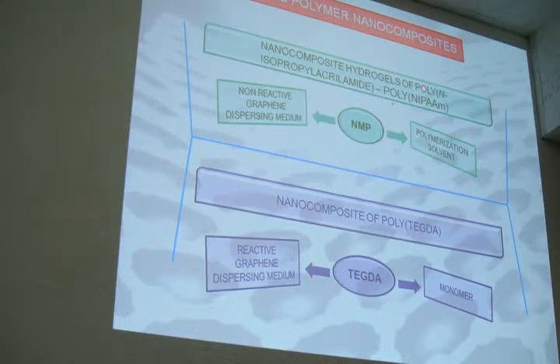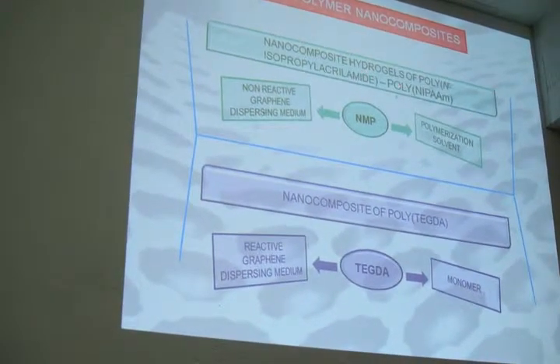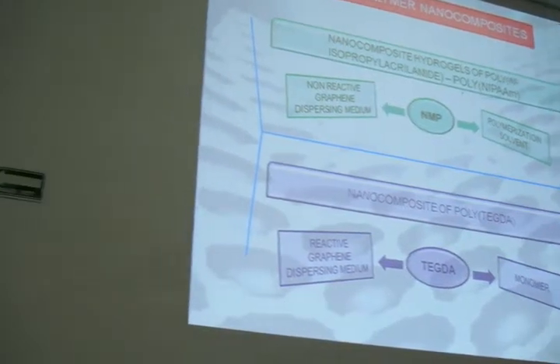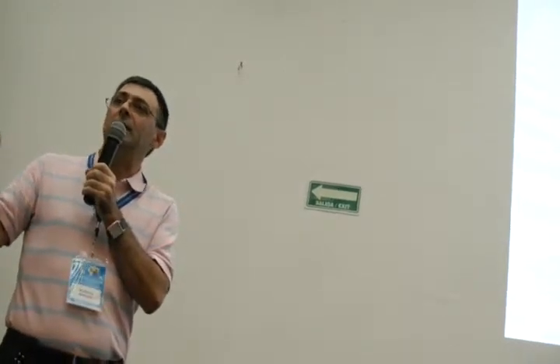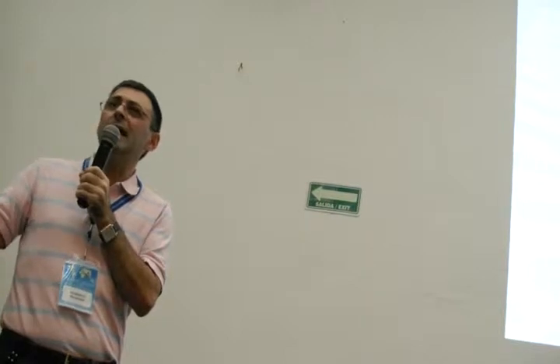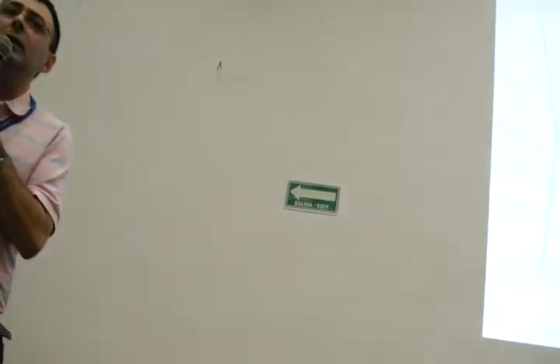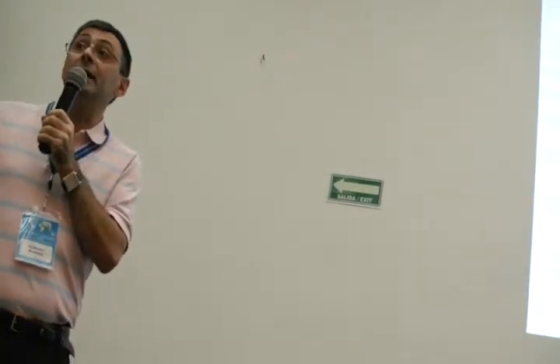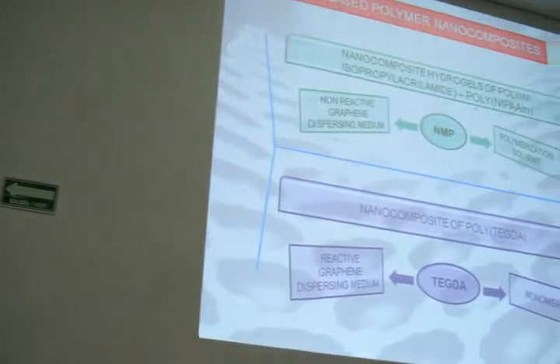In the first case, we prepared polymer nanocomposites in the form of hydrogels. Poly(N-isopropylacrylamide) is a well-known thermoresponsive polymer, and it is characterized by a lower critical solution temperature. Actually, this temperature is at 30 or 32 degrees, and below this temperature your hydrogel is swollen, but above this temperature, the hydrogel is collapsed. The idea is: what happens if I add graphene, in particular, what about the generally poor mechanical properties of a hydrogel?